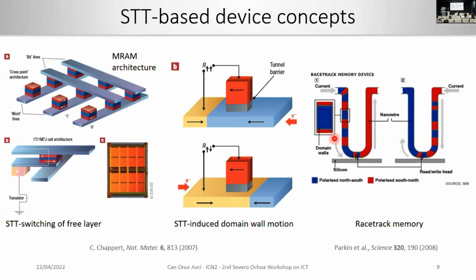Okay, so another way of using this current induced domain wall motion is to build a so-called racetrack memory, where in this kind of device, you can inject some current and move collectively all the domains in the material, such that you can store multiple bits of information in a single wire, and you can just put a read head in the proximity and read the domain information at that specific location, just right at the bottom over there. So these are the early concepts of using current-induced spin torque phenomenon.